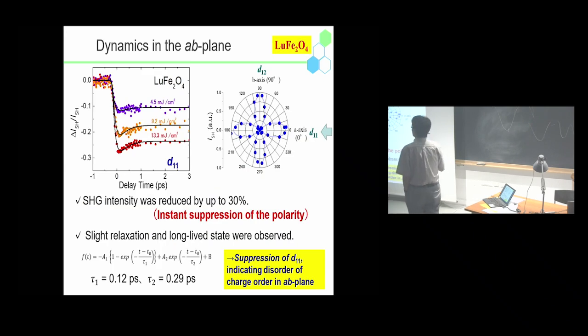Okay, I will show you the pump and probe data. This is the time dependence of the relative change of SHG at the d11 point. Just after the photoexcitation, you can see a huge drop of the relative change of the SHG intensity, down to 30%. This indicates the instant suppression of the polarity of these materials. After that, you can see a slight relaxation and a long-lived flat state.